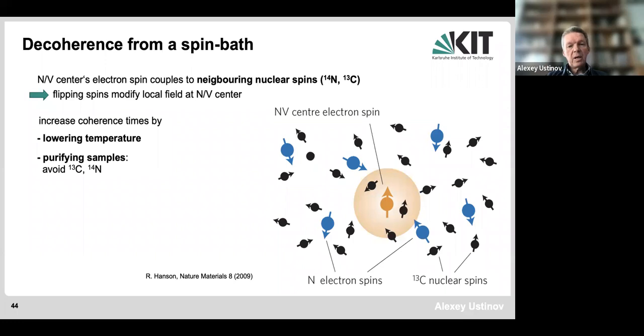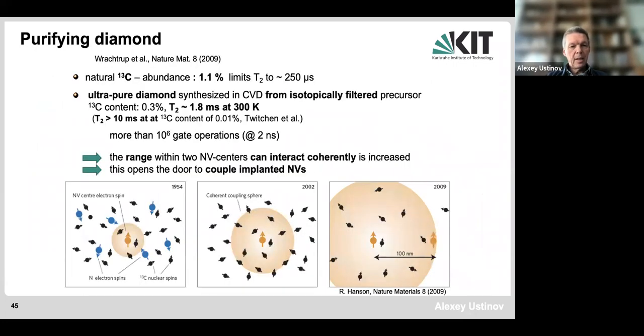Now, there are also other isotopes of nitrogen. This also has to be paid attention to. So nitrogen-14 has to be removed to avoid unwanted interactions of the NV center spins with the environment. Now, if one makes ultra pure diamond, which can be synthesized from isotopically purified carbon, then the dephasing times at room temperature increase from a fraction of a millisecond to several milliseconds. And if one purifies more and more, of course, this time increases further to tens of milliseconds and more.